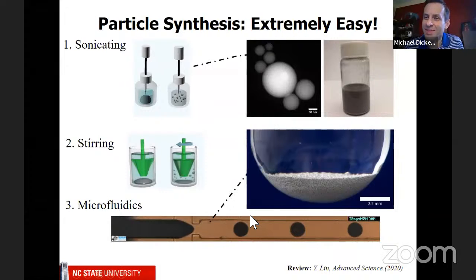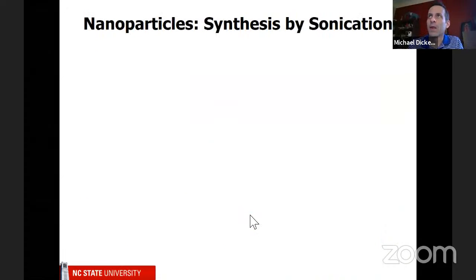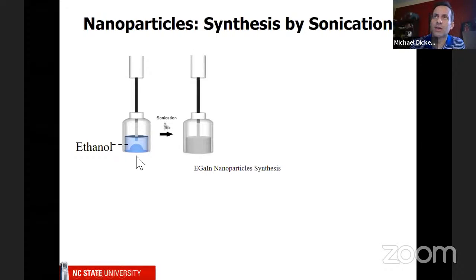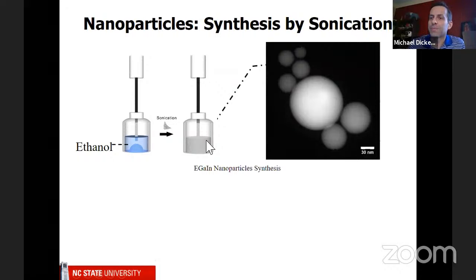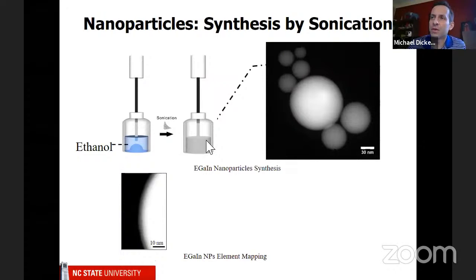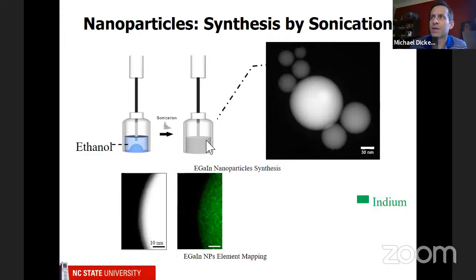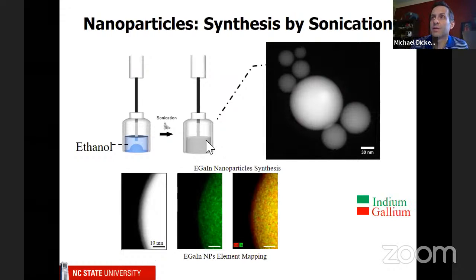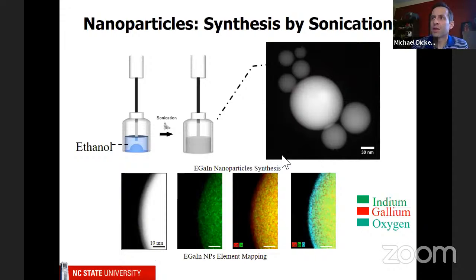Okay, so what is this good for? I'll show you a couple of examples. So I mentioned that one way to do this is by sonication. So again, you take some solvent and a droplet of the liquid metal, you sonicate it, which is just vibrations, and it forms particles. And this is what they look like. If you do an elemental analysis, you can see that there's indium in these particles, there's gallium in the particles, and then if you look at the oxygen, you can actually see the oxygen, the oxide that forms on the perimeter of this droplet on the outside.